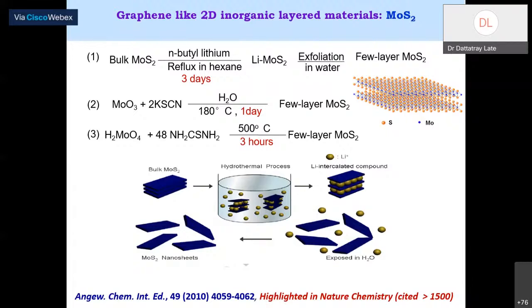Just imagine you have this paper, a layered sheet. Now lithium will go in between these layers individually. When you do simple ultrasonication and exfoliation, you will be able to separate out these layers of MoS2, from few-layer to multi-layer MoS2. Depending upon how you do the ultrasonication and exfoliation, this will determine the thickness of your material.